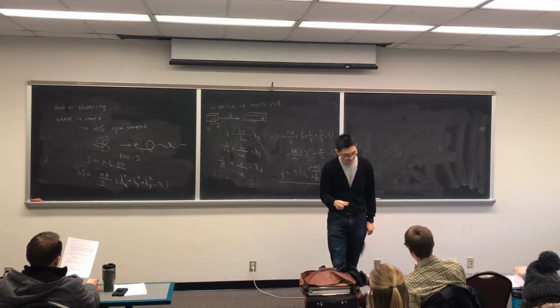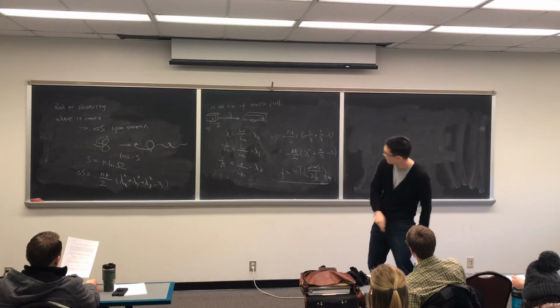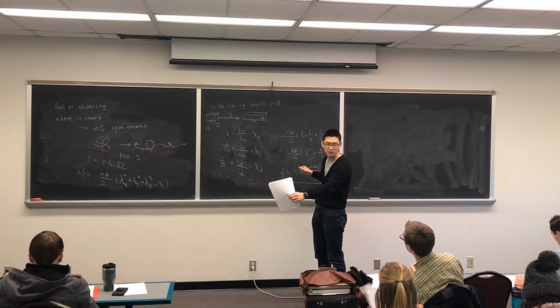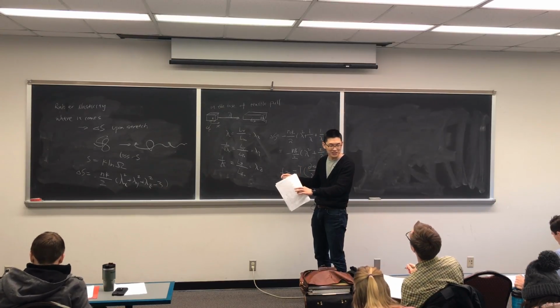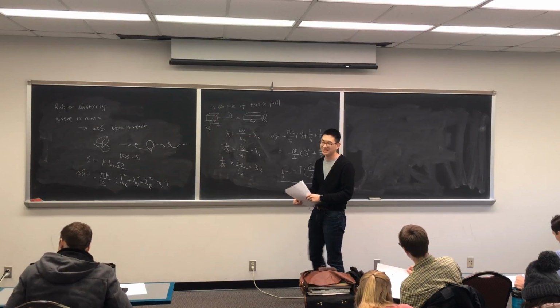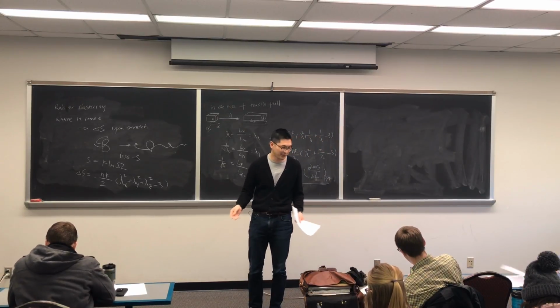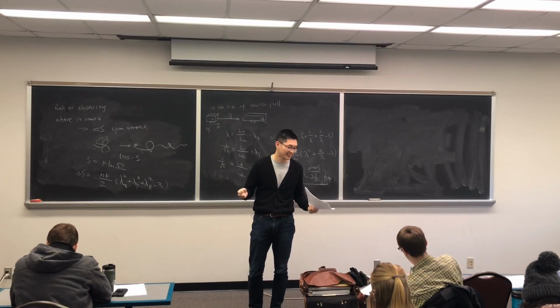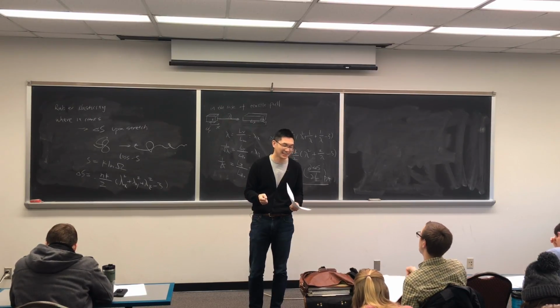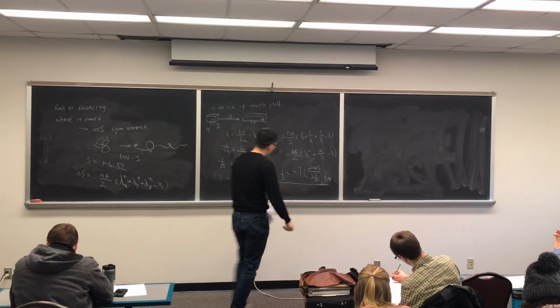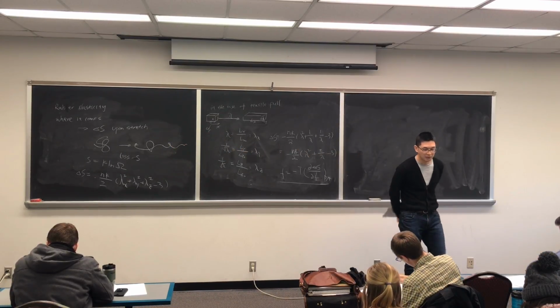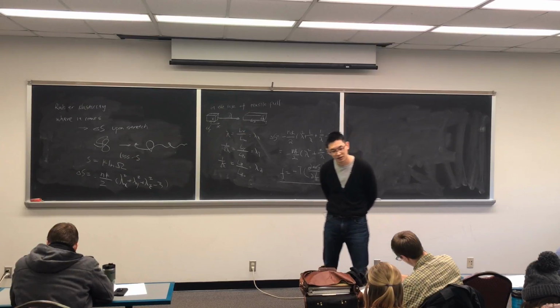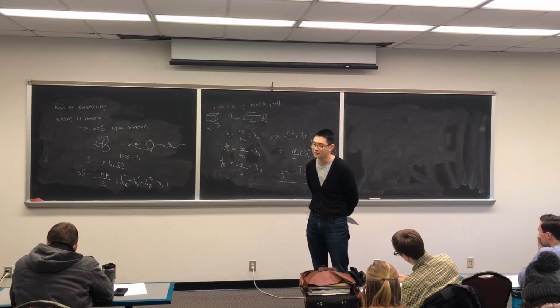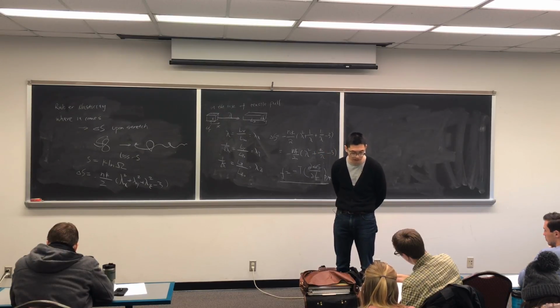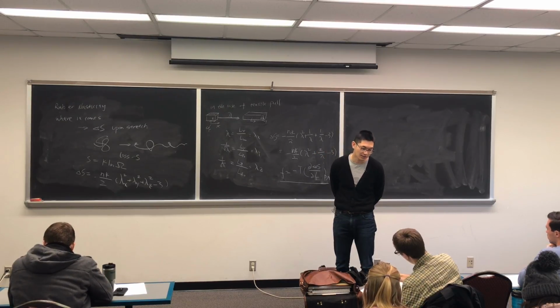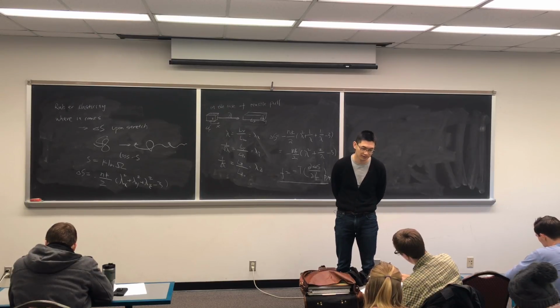Okay, so this one is per unit volume. Now the one without n is per single chain. Well, you just pull one chain, there are no other chains. But now we are talking about collectively. For example, in this class we've got 13 of you, so we're talking about 13 total number here. And you will later see why this comes into play, because when you have a real material, you need to consider the cross-link density, and that's related to this number n. The higher the cross-link density, the higher this n will be. Okay?